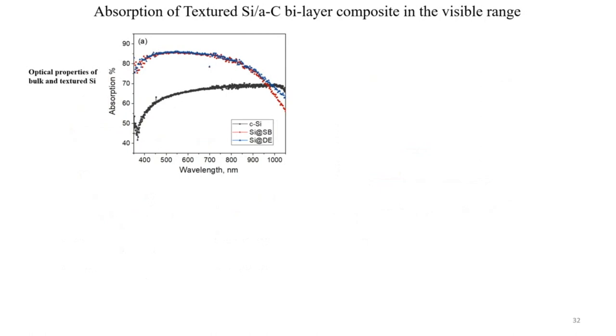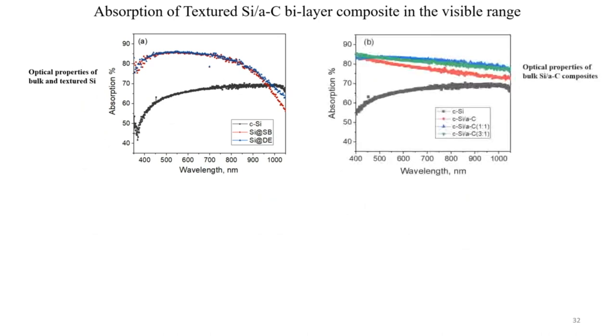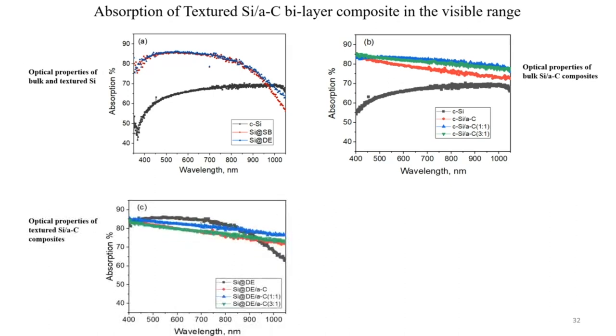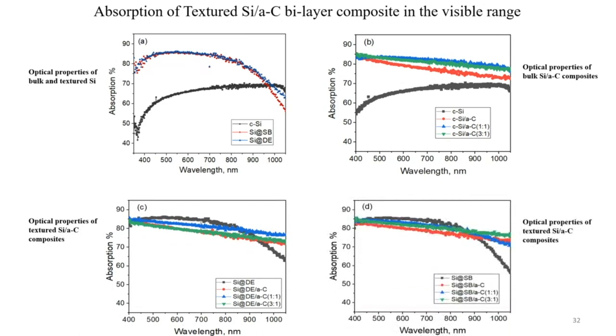So we further explored the optical properties. From figure A, we can see the light absorption of textured silicon surfaces compared with crystalline silicon, and we see a dramatic, significant increase in the light absorption. The next, figure B, also investigated the light absorption of crystalline silicon, this time with different amorphous carbon formulations on top of it. We have the continuous amorphous carbon layer and also porous carbon layers, and the absorption in the optical range of the electromagnetic spectrum increased dramatically. This was also seen in the case of the textured silicon surfaces from diatomite and also from silica nanoballs.